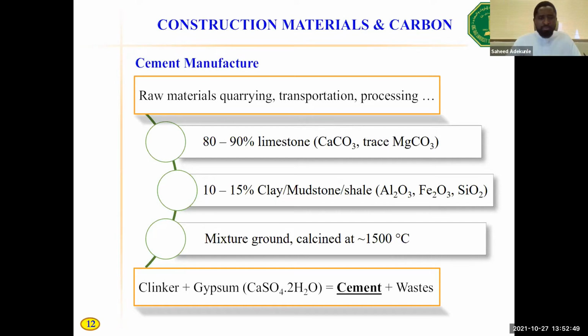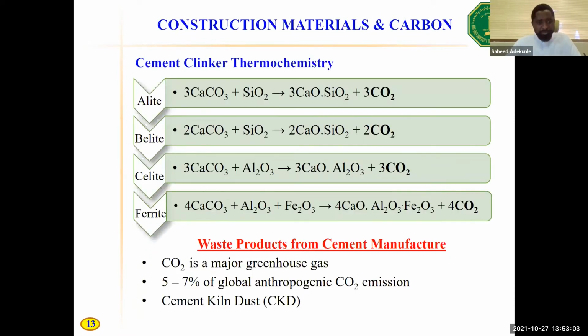As if this is not enough, consider the energy intensity of cement manufacture. Let's look into the chemistry of cement itself, or the thermochemistry of cement production. Cement, like I mentioned on the previous slide, you need high temperature to activate the raw materials. And this results in a series of thermochemical processes involving the formation of the major phases of cement, which are alite, belite, celite, and ferrite.